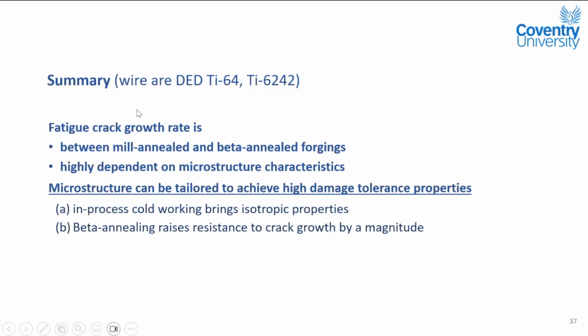I have a typo. Wire arc DED is between the mill annealed and the beta annealed forgings, and is highly dependent on microstructure characteristics. And because of this, we can make use of this by tailoring the microstructure to achieve high damage tolerance. So I don't think I have time to talk about modeling.